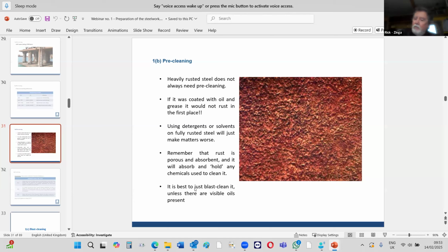Let it dry, come back, put another 3 or 4 passes, and you build it up to 100, 120. And we said to them, you want 5 years. Okay, that might give you 7, even 8 over rust, believe it or not. And as I said earlier, the pull-off values they got from our system was unbelievable. So this is how they start.